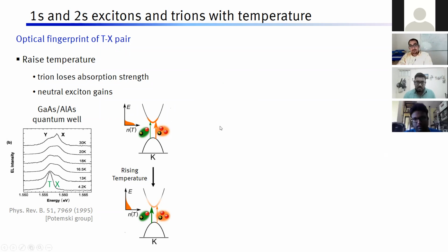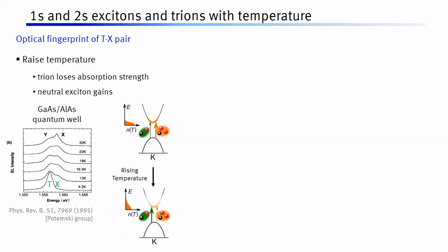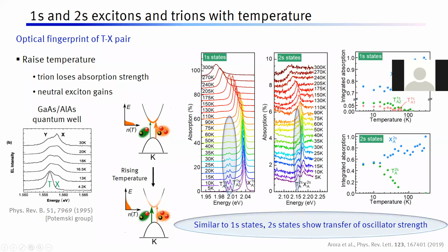Yeah. But even if we have, this will not follow this trend. So exciton will be larger and trion will be smaller. No, again, sorry. So even if it's an undoped sample, yes, even if we have a small trion signature, with temperature, trion will go down and exciton will go up. That is true. But in undoped samples, you cannot have trions in the first place. Whenever you have any trions, that means there is some unintentional doping. Yeah, but this will happen then. That is true.